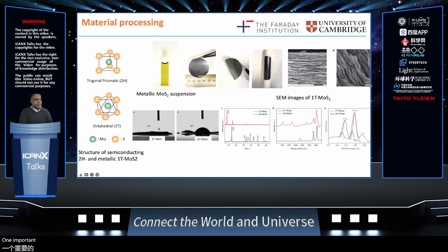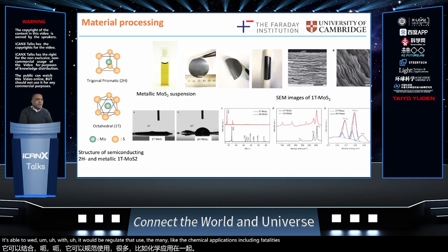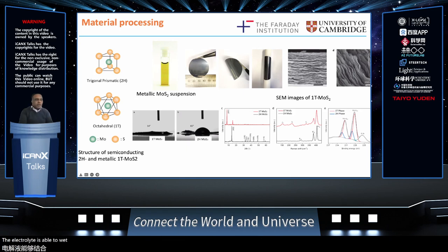One important thing to point out is that the metallic phase of MoS2 is hydrophilic or lyophilic. So it's able to wet with the electrolyte that's used in many electrochemical applications, including catalysis. The electrolyte is able to wet the electrode quite nicely, which enhances the interactions and reactions that we desire. We can then characterize our restacked electrodes in the usual way to confirm that they're 1T and have the usual properties.